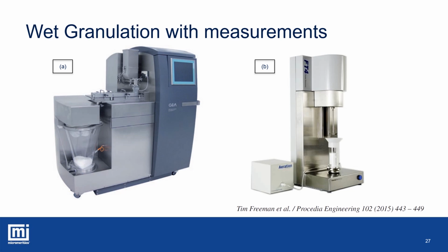it specializes in the measurement of dynamic flow properties. They use these to take two different formulations through wet granulation, then drying in a range of conditions to give granulated products. The basic flow energy, or BFE, was then measured.